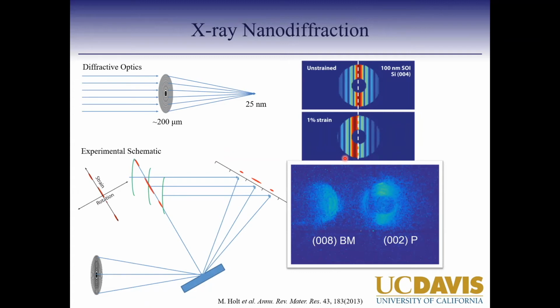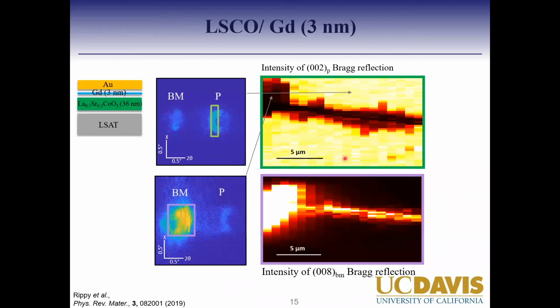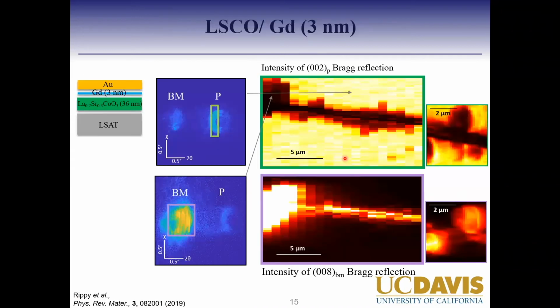What we have looked at is that our collaborators have done neutron diffraction with depth sensitivity. They've done it for magnetic systems. For magnetism, they can see that the bottom layer is fairly magnetic while the top layers are not, which is consistent with the fact that LSCO perovskite is magnetic, but the brownmillerite is not magnetic. Yeah, thanks, okay.